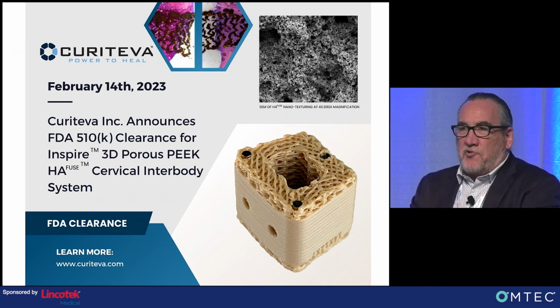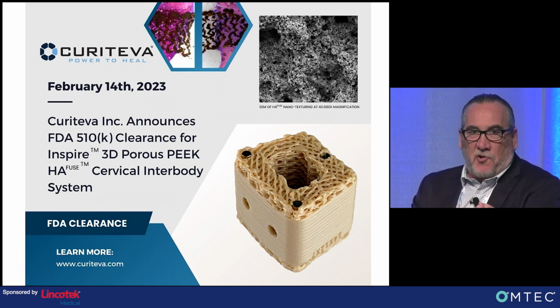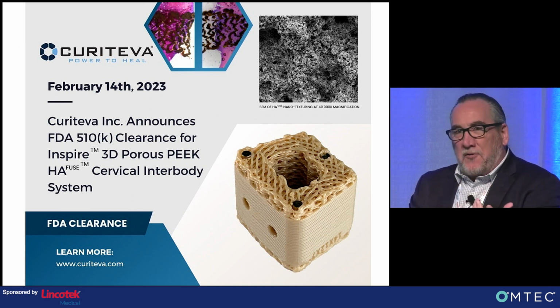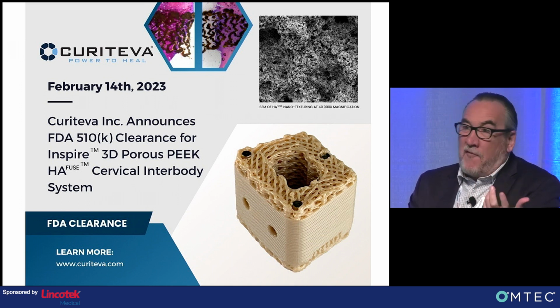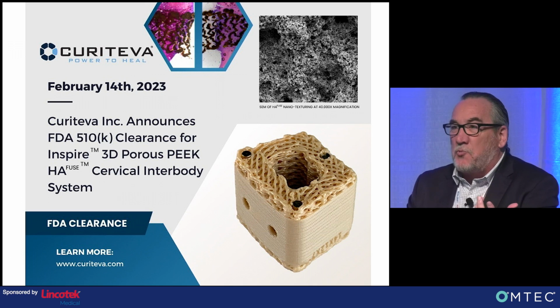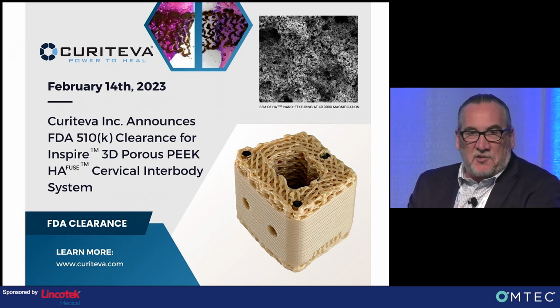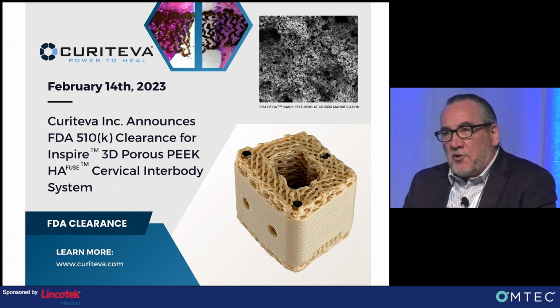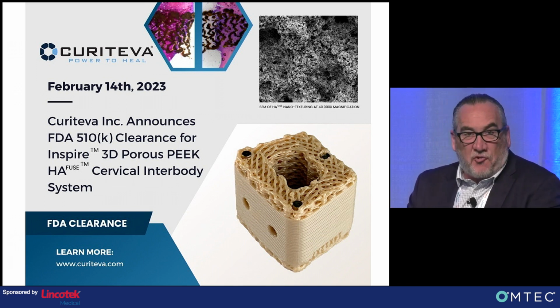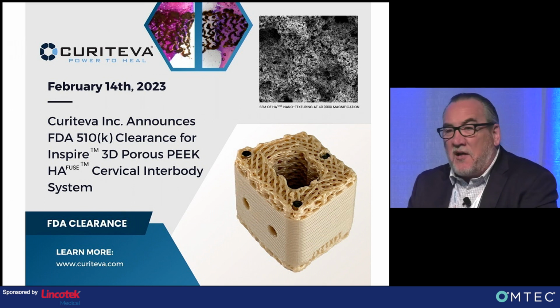But this pore structure lends itself to bone integration, full osseointegration. It does that through its structure. So if I were developing a bone graft, I would probably have an interconnected porosity that had a pore size distribution of 100 to 600 microns. It's well established in the industry and the literature as being promotive of osteoconduction. But the real trick is to make sure that this is strong enough, as Steve laid out in the beginning.